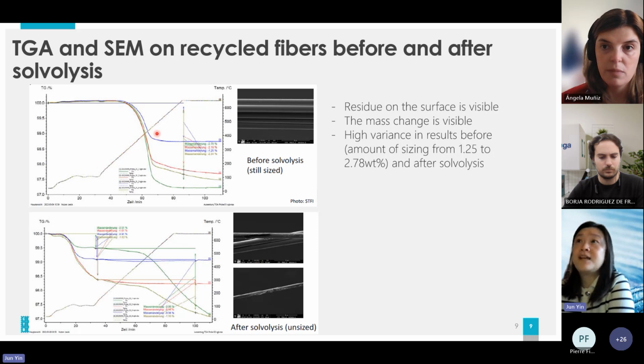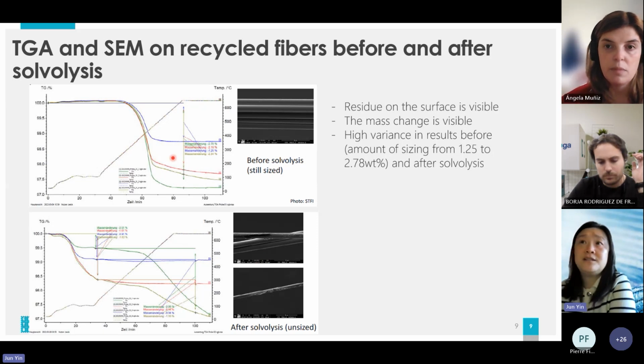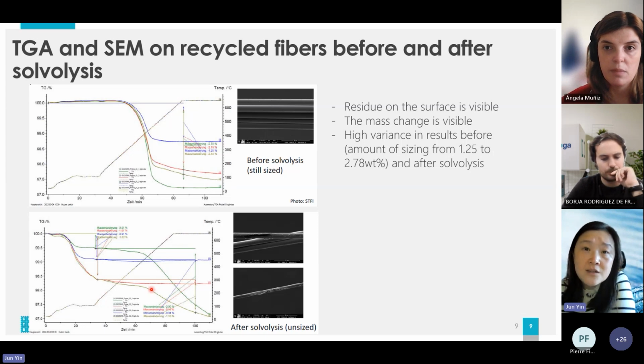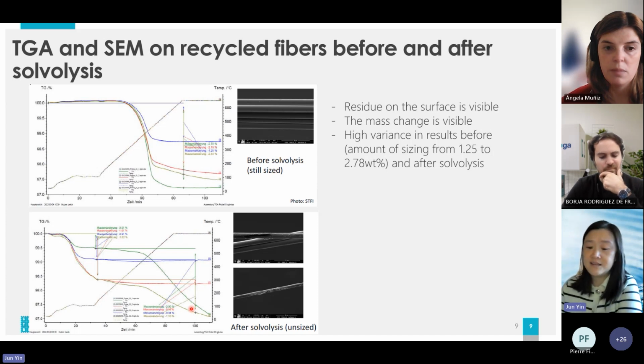The amount of sizing goes from 1.25 to 2.78% by weight, then decreases to a very low level. So that means the original sizing is generally removed during the solvolysis process.